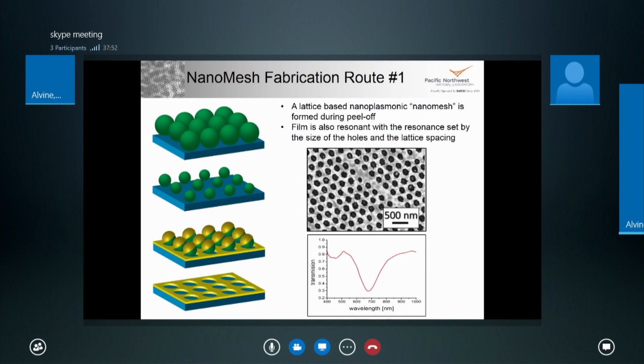In addition to the nanoshell structure, we essentially get for free a secondary structure, which is a nanomesh. You can see the SEM here. What happens is when we deposit the metal on top of the shells, we create the nanoshell, but we also get a shadow pattern on the substrate. So when you peel off the shells embedded in an elastomer, what you're left with is a series of holes in the metal. The bright region is the metal, and the dark regions are the holes in the metal. You can change the size of the holes and the spacing, and that will dictate the resonant properties of this pattern.